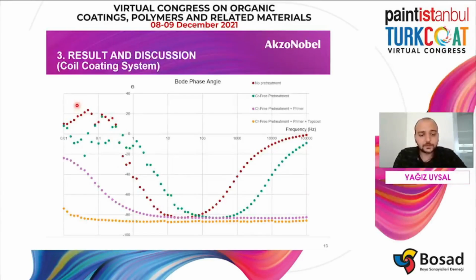And if we look at the phase angle diagram of different layers, it can be seen that the bare metal and the chromium-free pretreatment metals have similar behavior. At higher frequencies, the graphs start to increase. This indicates the panels started to lose their protective function. However, primer and the top coated metals kept their linear behavior even in higher frequencies. We can say that our samples have a high corrosion resistance.